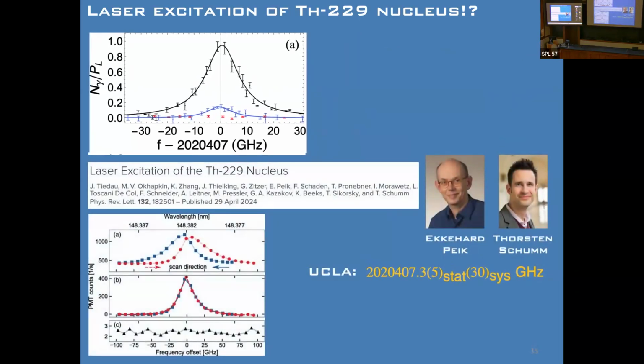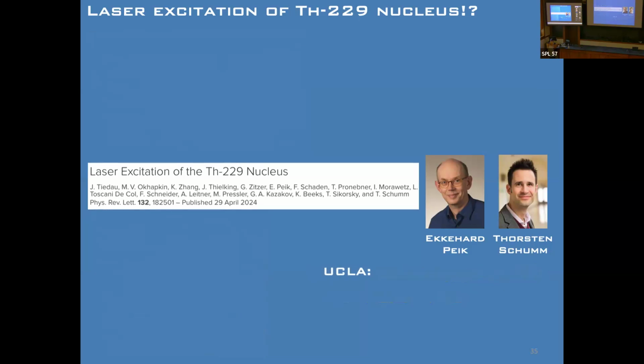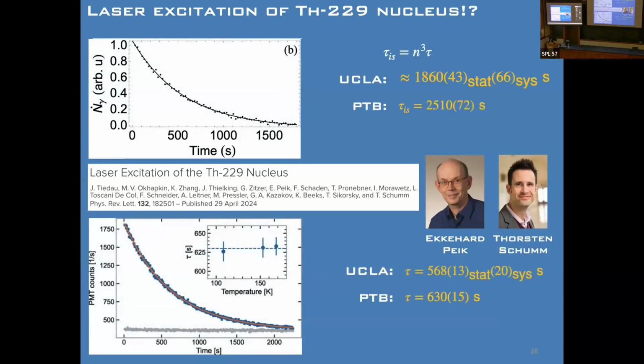Now, is this enough to claim you've seen the nuclear transition? In a paper that actually came out a couple weeks before ours, Ekkehard Peik, using crystals grown by Thorsten Schumm with basically the same idea, found a transition at 2020 409 gigahertz, but the error bar was about 7 gigahertz. So within error bars, these are the same. Their lifetime was very similar as well. You expect the n in calcium fluoride, because it's such a well-known material, has been measured by NIST. And so that gives you about a 2,500 second lifetime. And so, within error, these are totally fine.